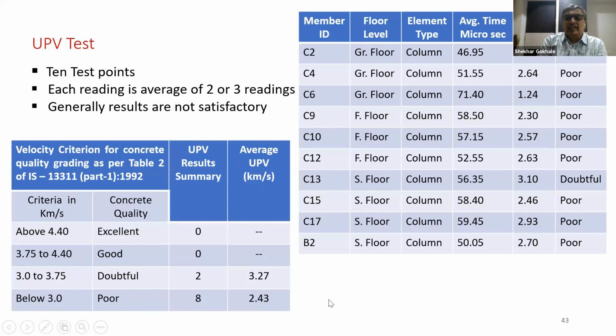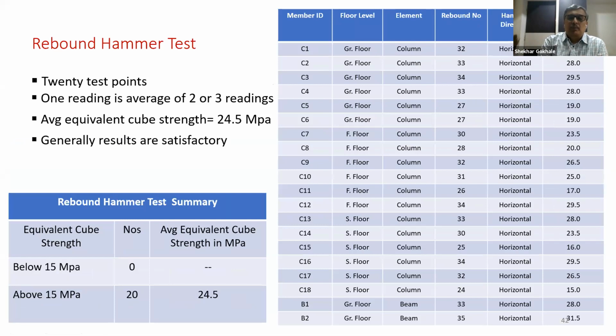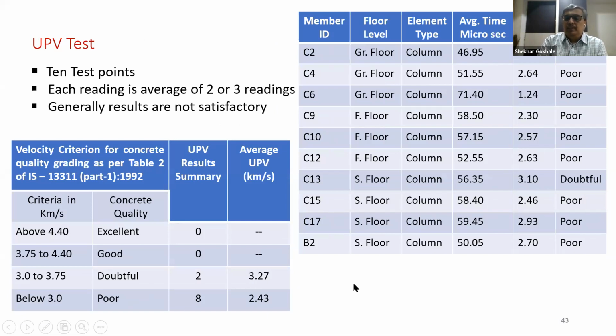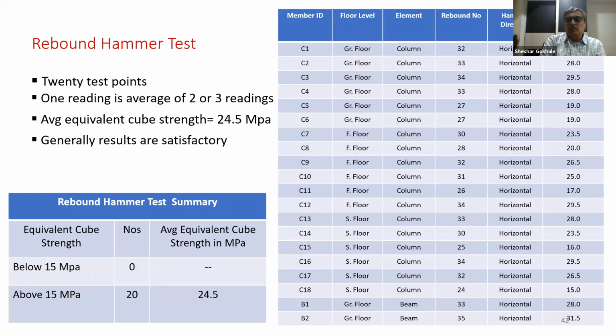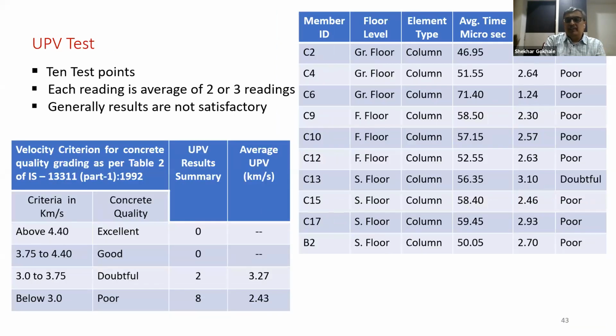So these two tests are giving contradictory results. Your rebound hammer test is giving very good results, and this test is giving poor or doubtful results. So this indicates there are cracks in the concrete. UPV test results are low if there are micro cracks inside the concrete, or the homogeneity of concrete is not good. If the concrete is not properly densed or compacted, then the UPV results are low, indicating it is doubtful or poor quality concrete. So even though rebound hammer is giving good results, the ultrasonic pulse velocity test is giving very unsatisfactory results.